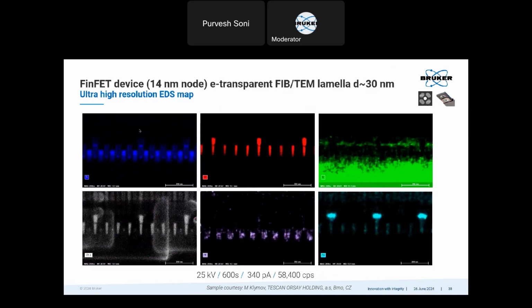This is a STEM sample. So again, a FinFET device, but with 14 nanometer node technology. Electron transparent sample, and the thickness of the sample is only 30 nanometer. And you can still see how nicely we could see all the layers. Again, there is a strong overlap between tungsten, silicon, hafnium, and tantalum. We could still separate them. Of course, tantalum L lines were used for this map.